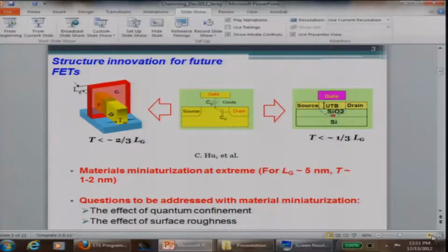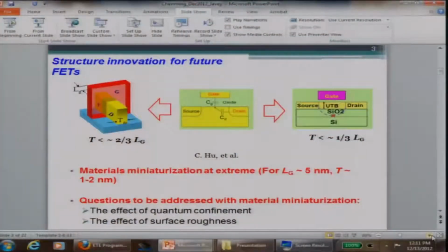So of course, the FinFET, you can see, has some electrostatic advantage over the ultra-thin body device. So you can play around with this, put in a gate length of 5 nanometers. That's what we should be thinking about, especially academics. And if you do that, then you can see that the thickness of the fin or the ultra-thin body device that you need is going to be just 1 or 2 nanometers.